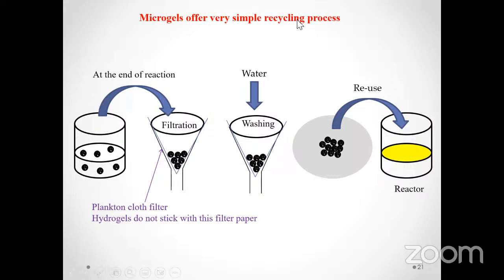However, when you use hydrogels or microgels, as we have used in our system, then the nanoparticles are encapsulated inside a microgel particle. A microgel particle may contain 10, 20, or even 100 nanoparticles, depending upon its size. So due to the larger size of the microgel particle, these nanocatalysts can be easily recycled by a simple process of filtration, as shown in this figure. When the reaction is completed, you can just filter the catalysts. The product will pass through the filter paper, and the catalyst can be recycled. This recycling can be carried out by simple washing with the solvent or with water, and then the same catalyst can be reused for its catalytic role in the next reaction.